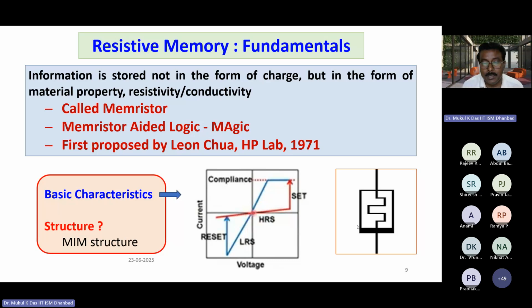So for example, in this figure, if you see, from 0 volt, if we start increasing the voltage, gradually current increases through a red line as shown here. Up to a particular voltage, very small current is flowing through this resistance, but suddenly it jumps to a high value of current. That means here the change of slope is very drastic. We can say the resistance drastically reduces at this point. So throughout this journey from 0 volt to this voltage, we obtained a low current and also a very high current. And when it is flowing very high current, then it is called set state. So resistance is becoming very low.